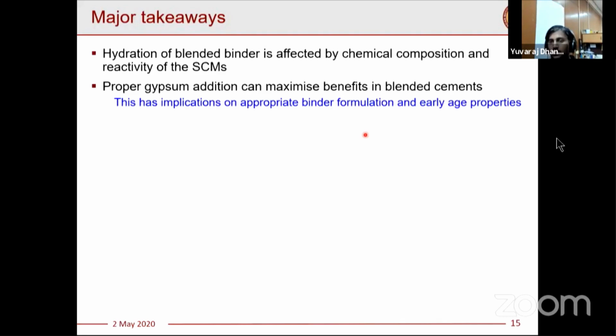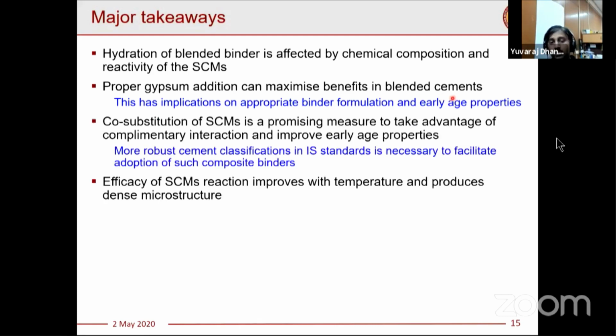So let me come to closure. The major takeaways are, when you start using these SCMs in cement, there are other characteristics which you need to look at and make sure the reaction is proper. Hydration is affected by chemical composition and reactivity. Proper gypsum addition can maximize the benefit in blended cement to a great deal, in blended mineral admixtures with reactive alumina in it. This has major implications on early age properties.